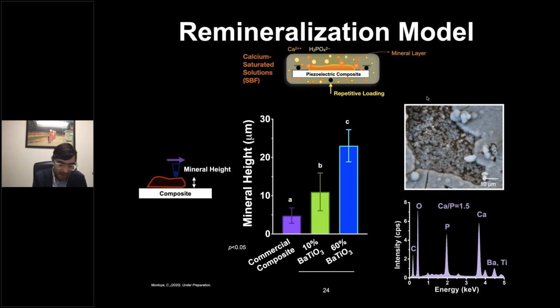The first thing we measure is how much mineral forms—we use a profilometer and measure the height. We have 3 groups: the commercial control, a group with 10% BTO (low charge), and a 60% BTO group (high charge).